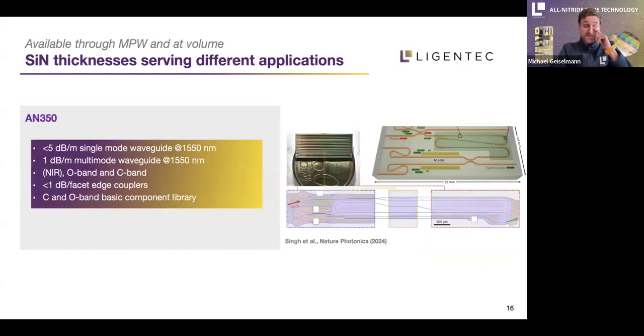The AN350 nanometer platform has very good loss performances in a single mode waveguide down to 5 dB per meter. In a multimode waveguide, even below 1 dB per meter at 1550 nanometer wavelength. And usual wavelength ranges that are addressed with this platform are O-band and C-band, and some of the applications even go down to the near infrared. Here again, we have facet edge couplers for below 1 dB per facet, and a PDK for C and O band.